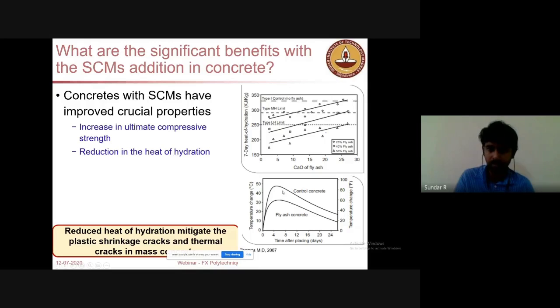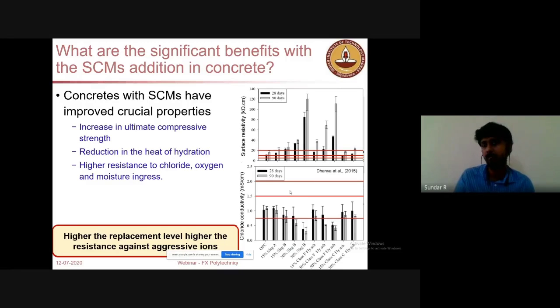If you see here, controlled concrete and fly ash concrete have much different heat emission. The temperature changes are way lower in fly ash concrete in comparison with controlled concrete, that is, ordinary Portland cement. So the reduced heat of hydration can avoid plastic shrinkage and thermal cracks. That was a huge problem earlier. When you go the next day after construction and see cracks on the concrete, there will be a huge dispute between the client and the contractor. So it is one of the huge issues.